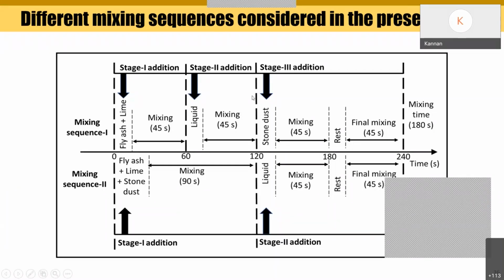So then we have just selected the workable range of moisture content, like below 10% it is unable to bind our raw material composite, and after 15% it shows the bleeding. So we have selected this particular range from 10% to 15% for our study.